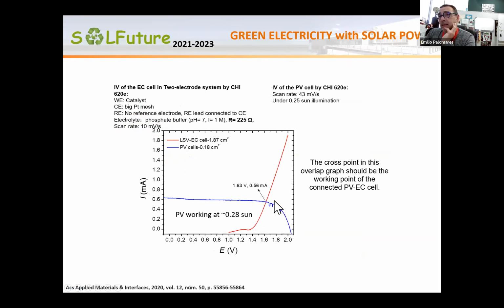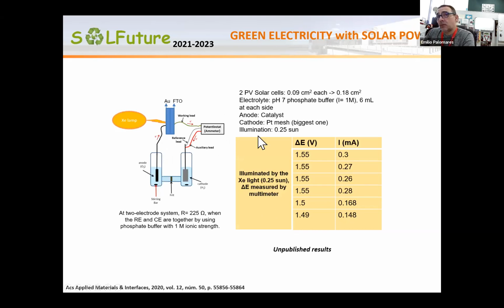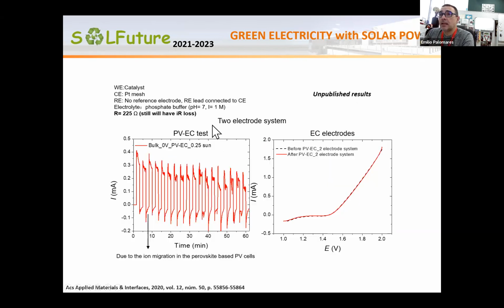This is the electrocatalysis. This is the point where you have to work in order to have the catalytic process going on. And this is a classical or rudimentary system we use to do the water electrolysis at the ICIQ. This potentiostat is what you replace with a solar cell. Basically, this is the on and off we observe when we do this. And at that time, what we saw was this kind of spike and then recovery. Then we learned from a paper published by Michael Grätzel that it was due to the ion migration in the perovskite solar cell. So in order to avoid that, you have to use chopped light.